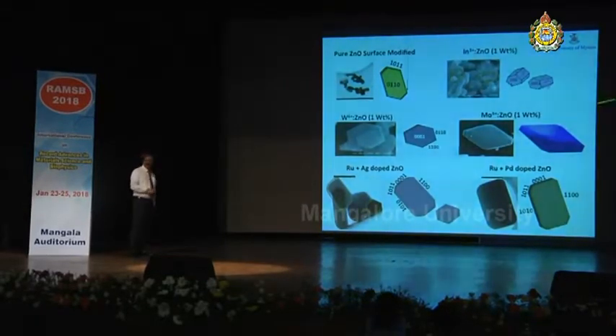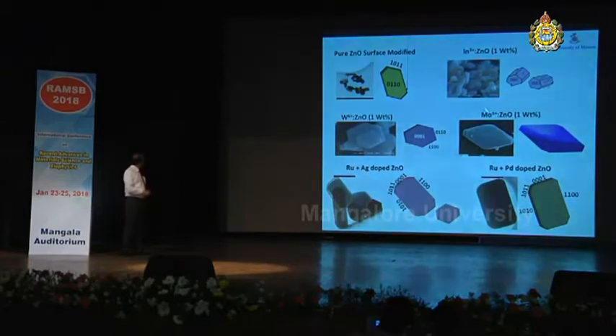These are some of the SEM images along with the schematic diagrams of these metal oxides, pure and doped. Here you can see the pure zinc oxide surface modified, showing this typical morphology and the facets which are indexed. And when indium is doped into the zinc oxide, you get a different morphology. And when you have tungsten, you get hexagonal platelets.